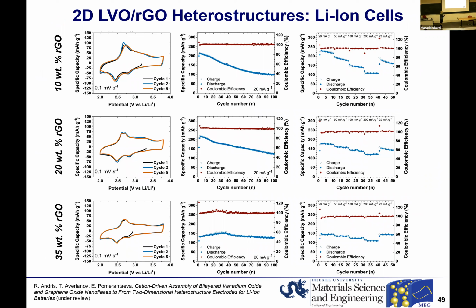Now, for the material that has 20% and 35% of graphene oxide, the electrochemical stability and also rate capability is much, much better. So this tells us that, yes, this formation of the two-dimensional heterointerface definitely has very positive effects on the electrochemistry of the final structure, because the CV curves still look like the CV curves of bilayered vanadium oxide. So oxide redox activity is there, but the stability is much, much better.